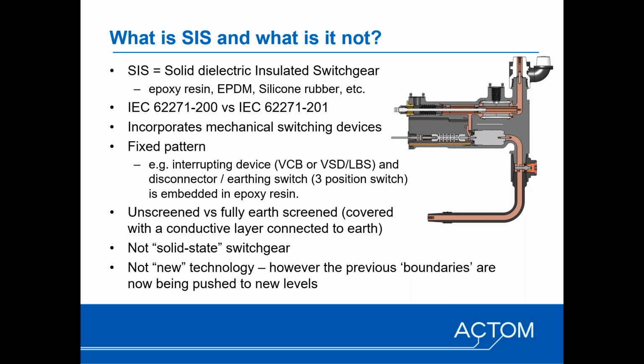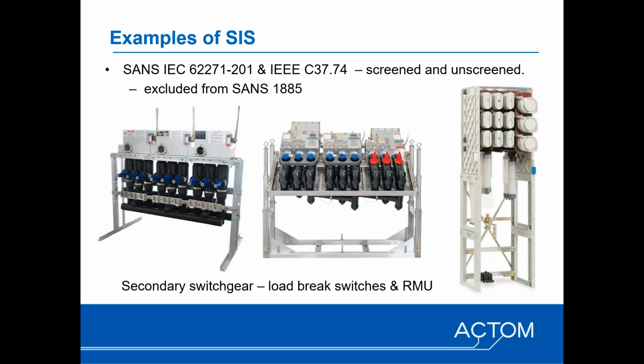The other point to mention is that effectively it's not a new technology. This is not something that suddenly appeared. However, what we've seen in the industry is there's been some drivers, for example, the drive to move away from SF6 and other fluorinated gases to more environmentally friendly insulating mediums. So that's been a driver, but also developments in the solid dielectric technology has really started to push the boundaries in terms of the ratings that can be achieved, both in terms of voltage as well as current. Today, most solid dielectric switchgear has been limited to secondary switchgear, typically rated up to maybe 630 amps and 12 kV.